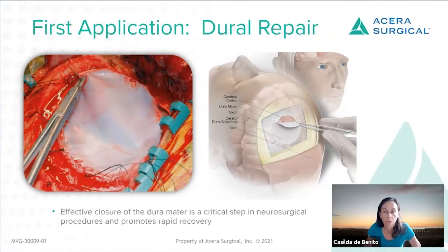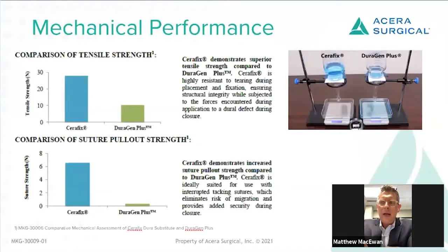And so what we did is we took the material, we initially compared it to some of the existing dural repair materials that were on the market, including Duragen Plus, which is a bovine collagen product that's very commonly used. We found that our material offered improved tensile strength and additionally barrier qualities that really were ideal for use in dural repair.